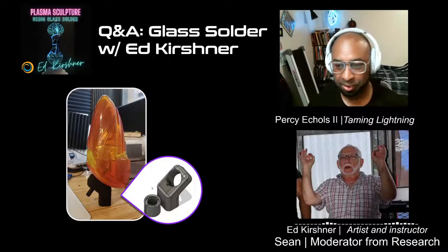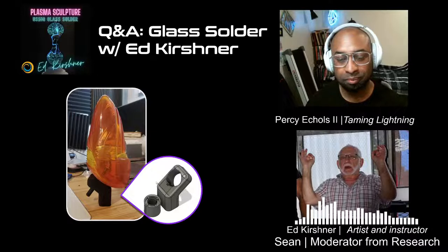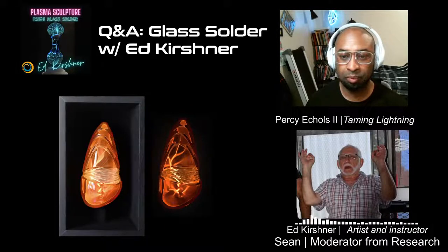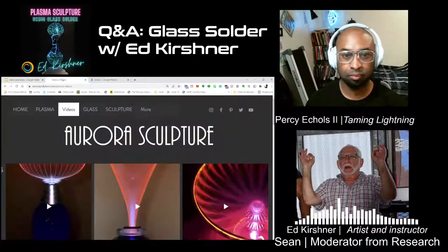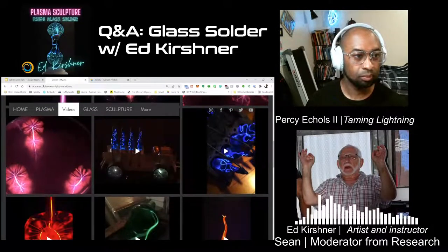So these other images are just me illustrating. Now, importantly, assembly. The whole question of beading and all of these others, that's only the solder when you have the gopping solder on the outside. The trick to make the best joint is to have very tight fitting lapping, where the solder is lapped between two pieces of closely fit glass. Then you don't have any problem with it beading or crystallizing, it just fuses. You're basically cold working with solder. Yeah, the cold work is very important.